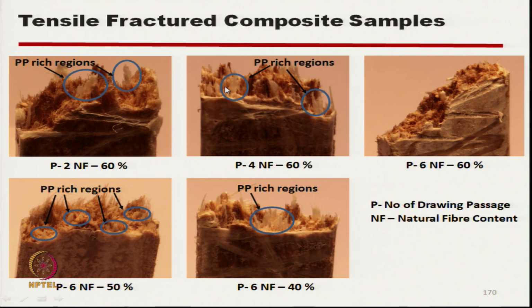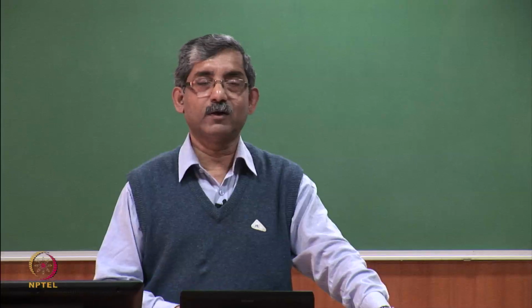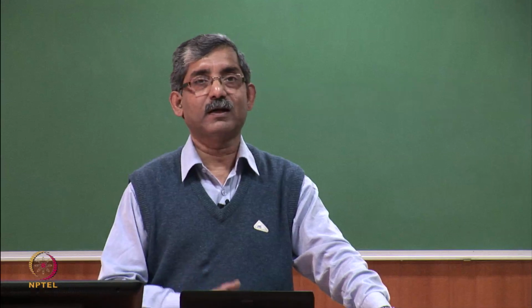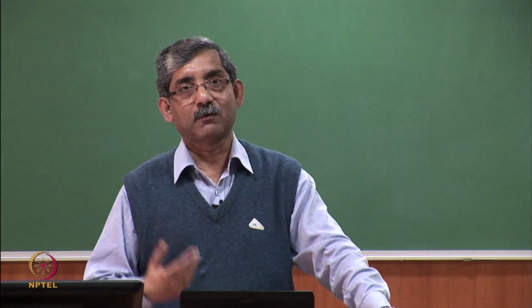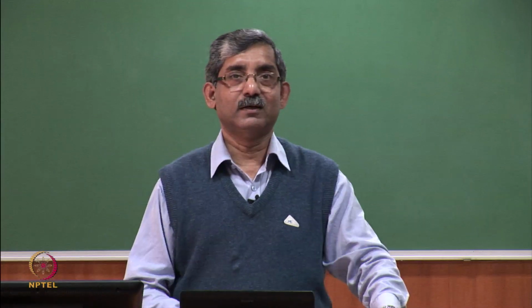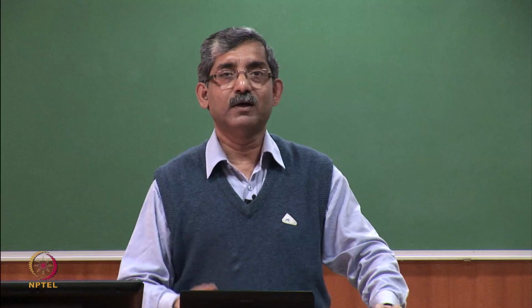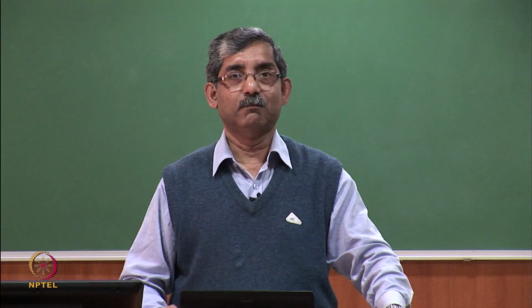Even at 4 drawing passages we can still observe the polypropylene rich zones, but when we increase the passages to 6, these are uniform. So, basically, if we have to produce the thermally bonded roving using natural fiber and, say, thermoplastic matrix fiber, we have to use more drawing passages for better blending.